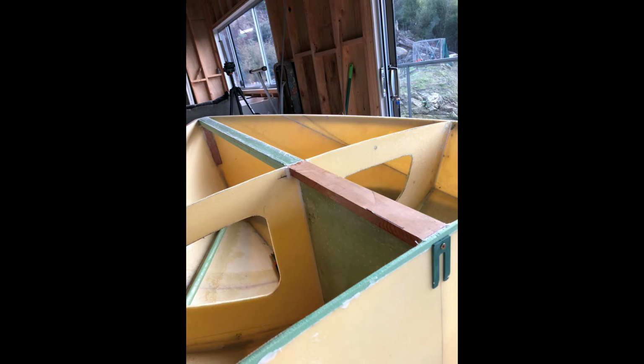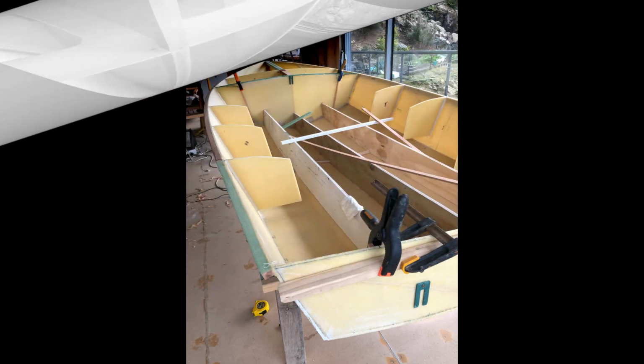I built the front half of the deck beam from foam with unidirectional glass top and bottom, and underneath the mast area, I made that from solid wood. Underneath that, a full foam bulkhead with glass both sides is lighter and much stronger than what manufacturers are currently using. They tend to cut it all out and make it of plywood, and that's mainly because of the technique they're using to fit the deck to the hull. But I think a full foam bulkhead there is a really smart move.